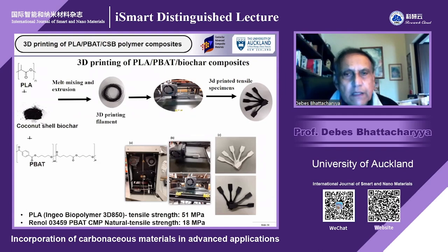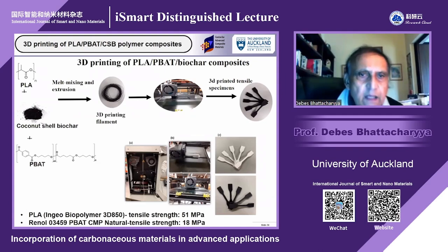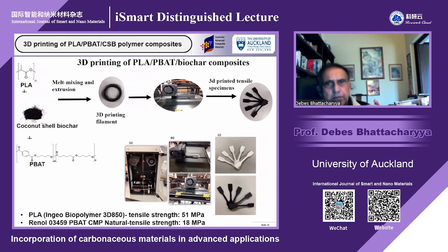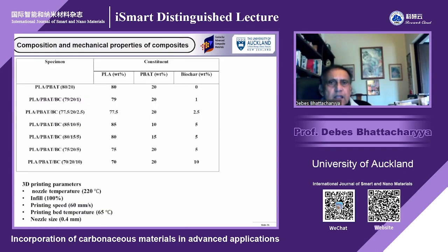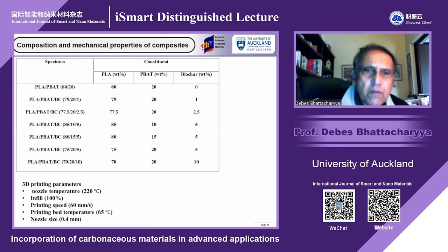Now, for 3D printing, we use a very similar technique. Prior to that, the filament was produced by melt mixing and extrusion, and then we produced the filament. We added PBAT, because PLA is brittle, so we had to add some PBAT there. PBAT adds some ductility, and then the biochar composites. We produced dog bone specimens and other types of specimens also, without any problem. These are the various combinations we have used, 80-20, 79-20, all these mixtures.